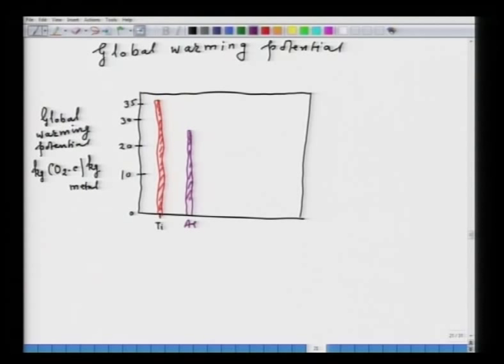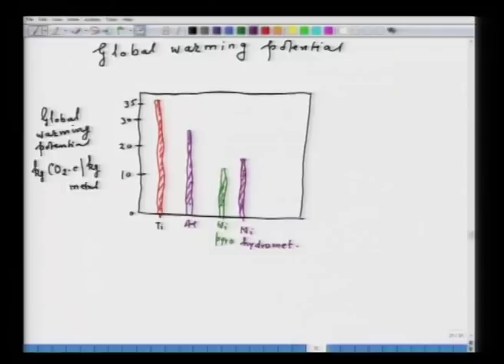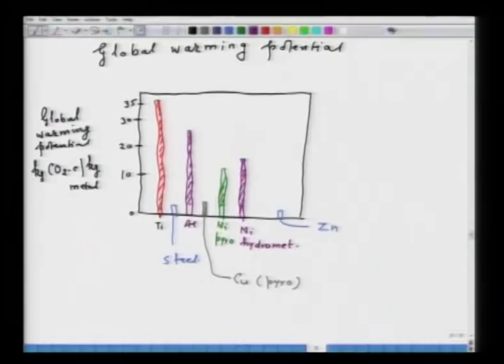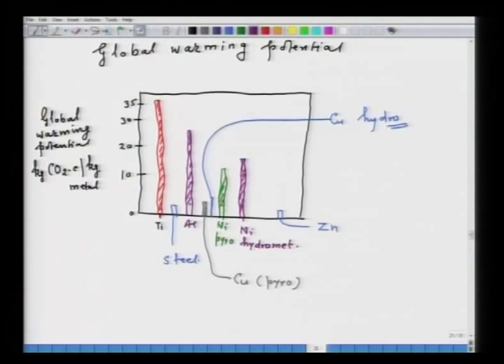Now, the quantification which I have shown on the ordinate is more or less approximate. I will give you the reference from where I took the values, so if you are interested, you can go to the original reference and update yourself. Say for nickel, this is for the nickel pyromet route, and this is for the nickel hydromet route. Well, for zinc, it is quite small. Similarly, for steel, it is also very small. This is for zinc, this is production of steel, and somewhere here we have copper, this one is copper by the pyromet route, and this one is copper by the hydromet route.